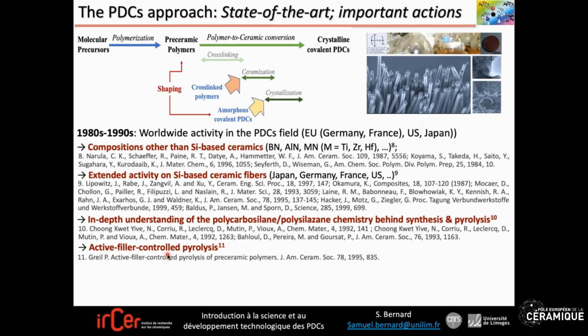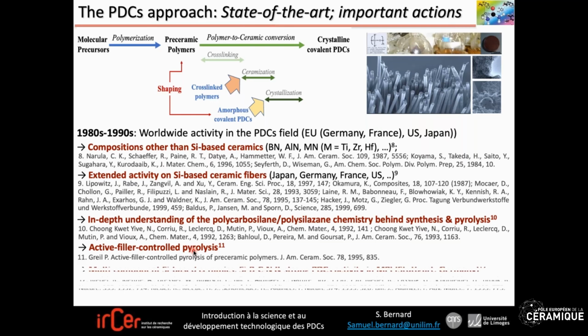A very interesting approach we will see later: Peter Greil from Erlangen, Germany, proposed active filler controlled pyrolysis. He mixed preceramic polymers with fillers, powders, in particular metallic powders, to reduce the volume shrinkage that occurs during the transformation of polymers into ceramics. So we will speak later about this potential.